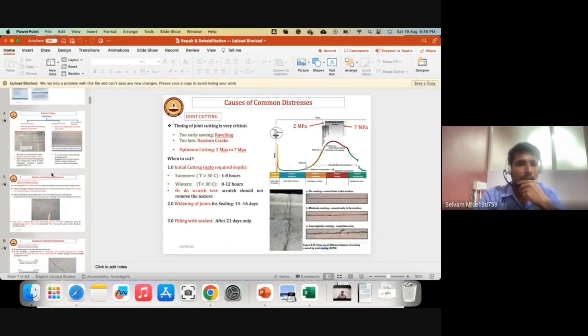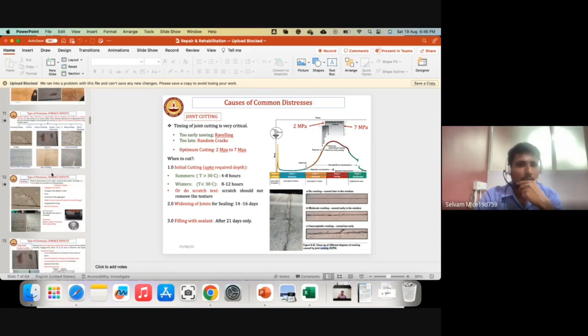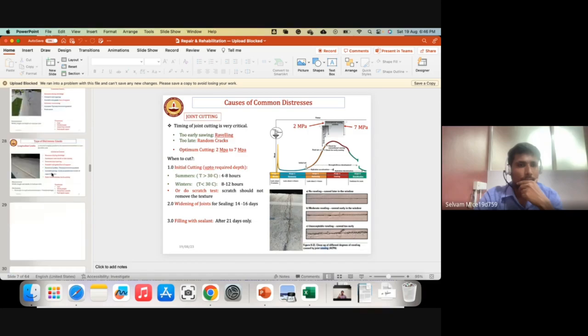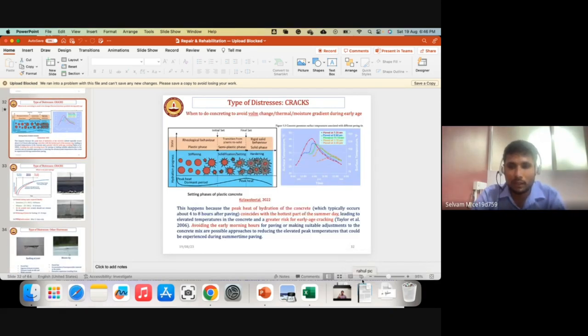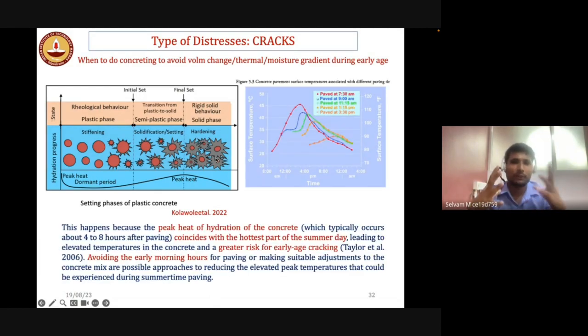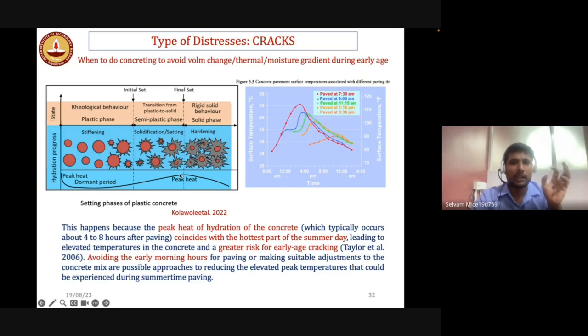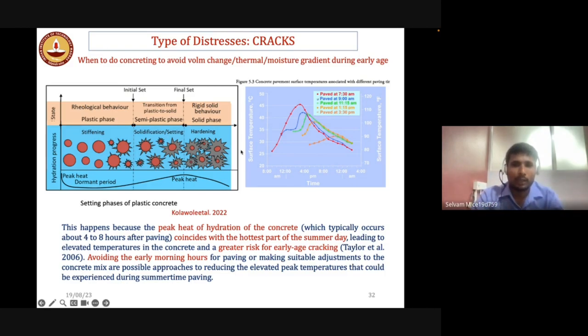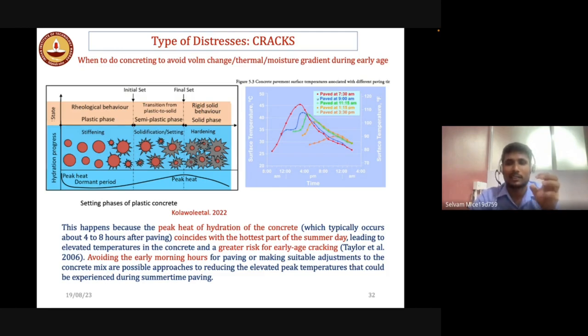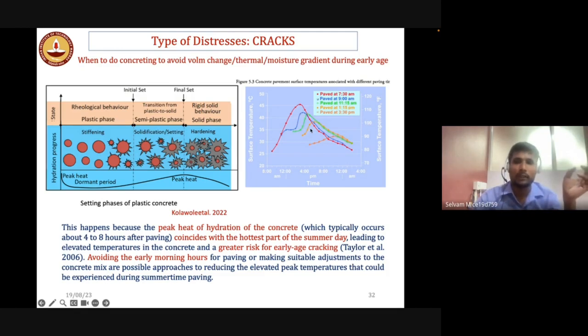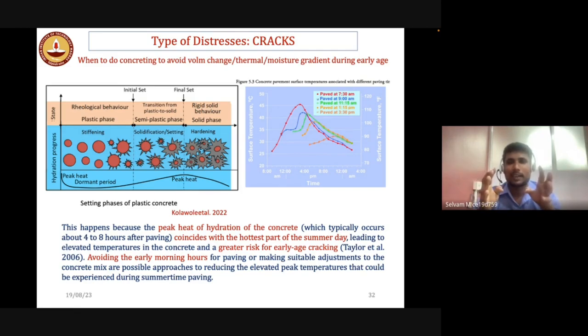Regarding the duration and timing of pavement casting: the chemistry of concrete involves a higher heat of hydration when cement is mixed, followed by a dormant period, then a peak hydration state that subsequently decreases. While laying the pavement, it must be ensured that the peak of cement hydration and the peak atmospheric surface temperature do not coincide. Therefore, construction should be scheduled for evening or morning to stagger these peaks and avoid early plastic shrinkage cracks.